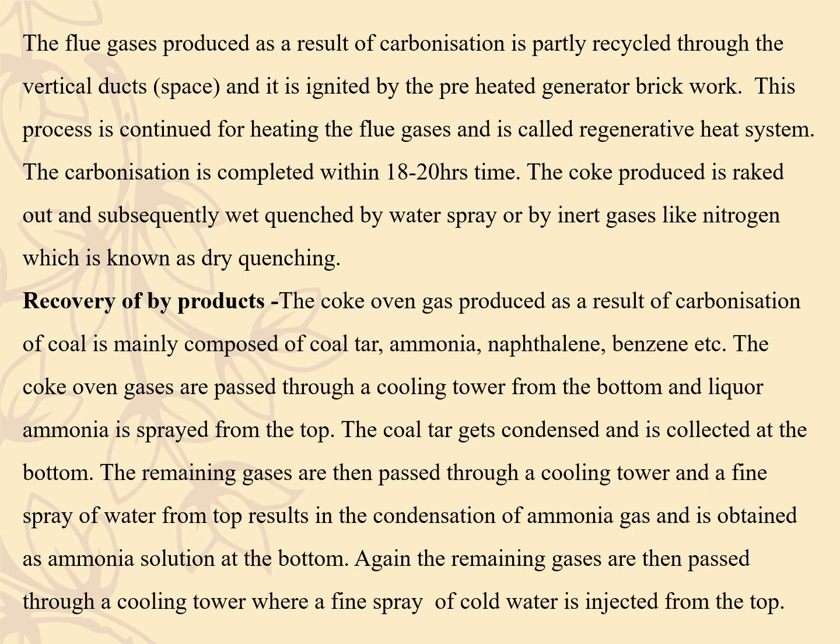The carbonization is completed within 18 to 20 hours time. But when compared to beehive, there it takes 3 to 4 days, whereas this is found to be an advantage. The coke produced is raked out and subsequently wet quenched by water spray or by inert gases like nitrogen, which is known as dry quenching.